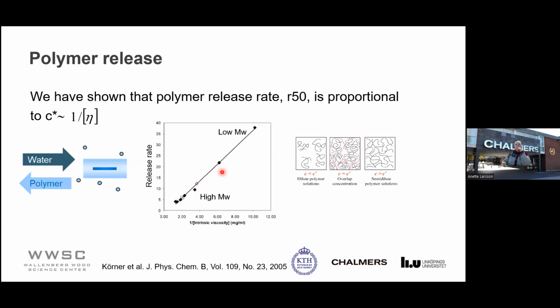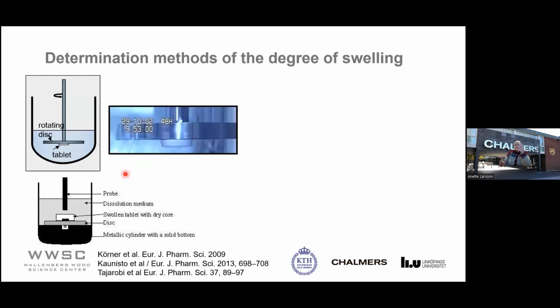So this is an indirect proof that the boundary here on the surface is directly related to the overlap concentration. Therefore, one can say that the degree of swelling and the overlap concentration is very important. So one needs to determine the degree of swelling. Then one can use something called a rotating disc.